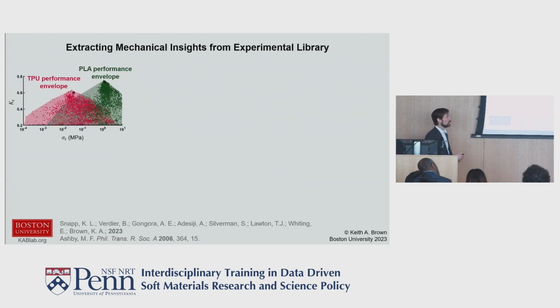Here's a plot that shows the efficiency versus the working stress of really all of the parts that we've studied for two different materials. This is the same thing that made Hierarchical, that thermoplastic elastomer. This is the same thing that made Willow, that PLA. And you can see what's highlighted are their design envelopes, the regions you can design. One thing that jumps out at you is that if you look at where they're peaked, there's really one value in the stress. So for a given material, there's a region in this space where the material is most efficient.